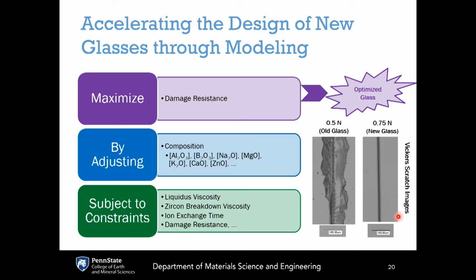This is one of our Gorilla Glasses that was designed in exactly this fashion, with the old glass here underneath a 0.5 Newton scratch load, and it's getting some nasty lateral cracks that not only look bad and feel bad, but also greatly compromise the strength of the device if you were to drop it, versus the new glass, which is under a 50% higher load under the same type of scratching and only responds in a microductile fashion.